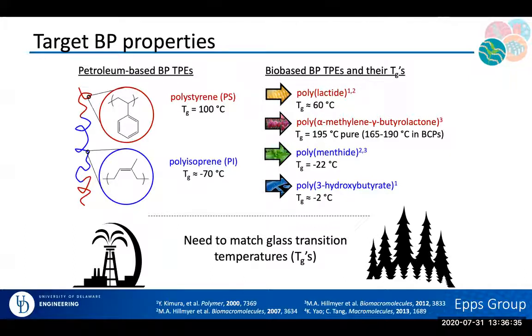I can obviously then switch to something like poly alpha-methylene gamma-butyrolactone, glass transition temperature of 195. So you might say, well, that's great. That's well above the temperature of boiling water. But one of the challenges there is that now I have to heat this material well above 200 degrees C in order to melt process that. So that's added energy input in order to make a material.